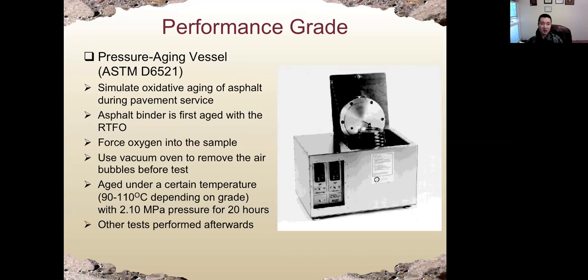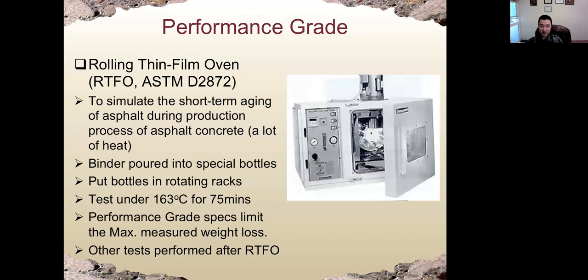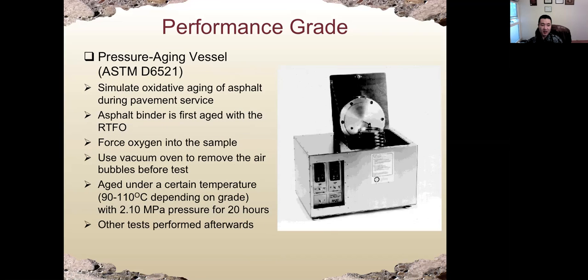For this test, the purpose is to simulate the aging process of asphalt over its service life, 10 years or 20 years. Okay, this is a slow aging process. The asphalt binder is first aged in the rolling thin film oven, the first test we just talked about. Then we force oxygen into the sample. The oxygen will age the asphalt binder over time, but it takes 10 or 20 years. How can we accelerate that process?